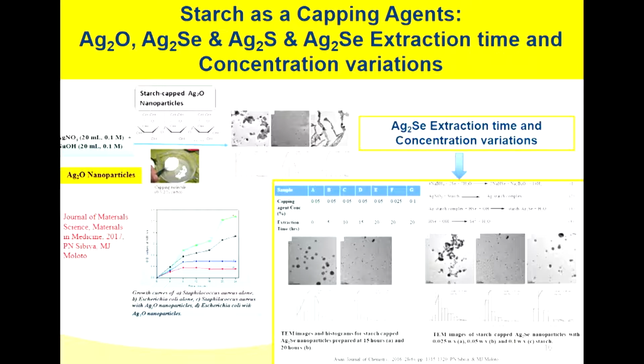such that if you do follow the extraction time, and also at the same time, just to vary the amount of silver that you'll be able to add into it, how effective will the particles be able to form? You can see that especially for these two here and these three here, that particles are still very nicely loose, and therefore it means starch is still giving such kind of improved, less agglomerated particles and more dispersed ones. And also at the same time, we thought if we are able to bring in this element of biomedical applications, why not we try and start doing some applications, and we explored some antibacterial activity where we realized that indeed they're showing very good signs of antibacterial activities there.